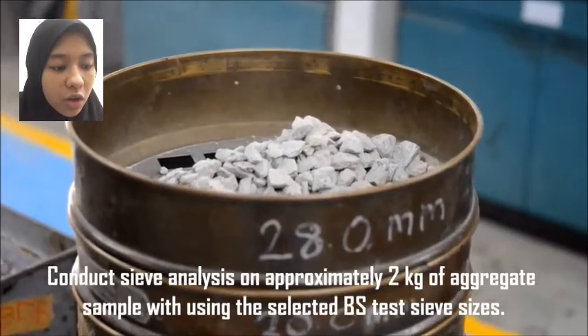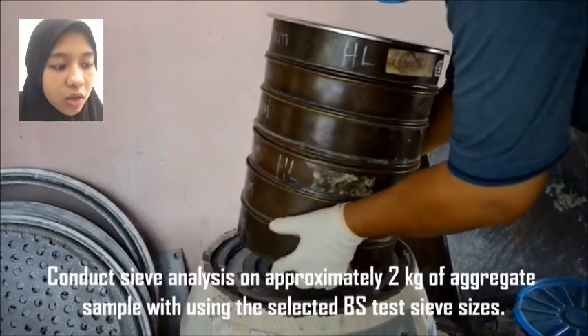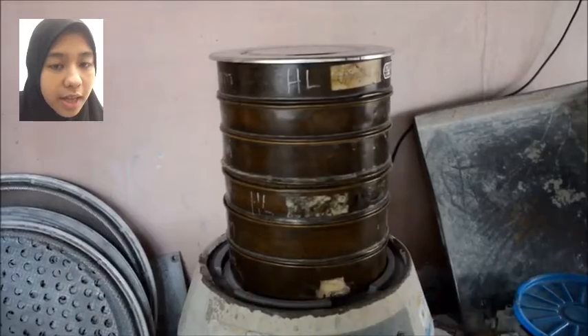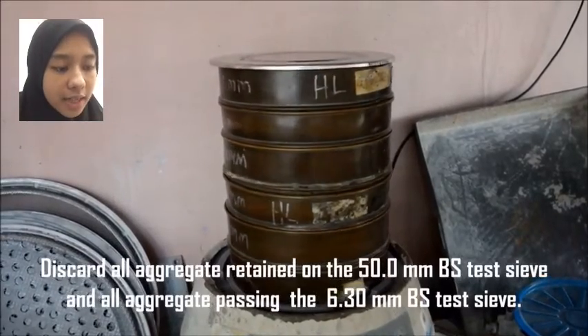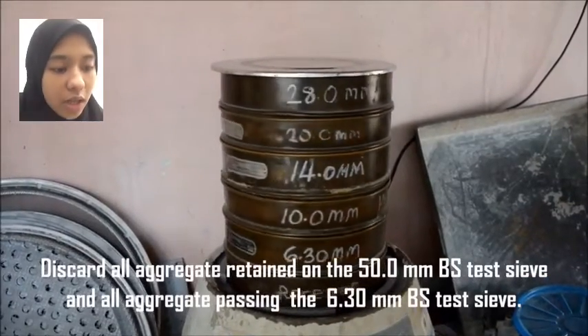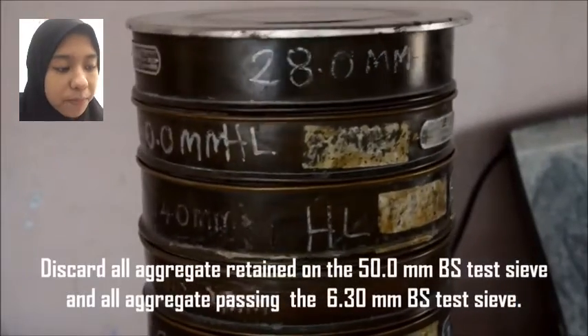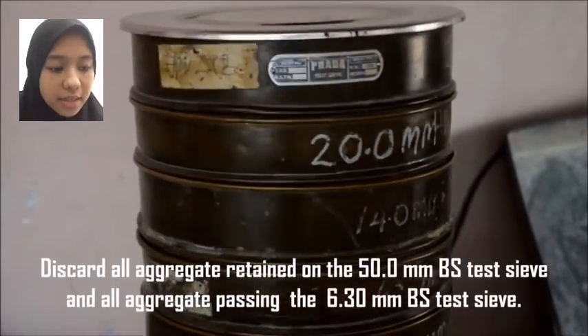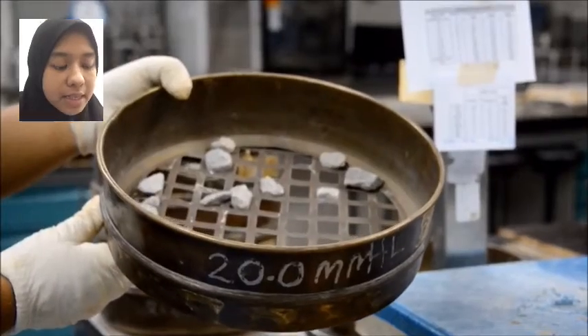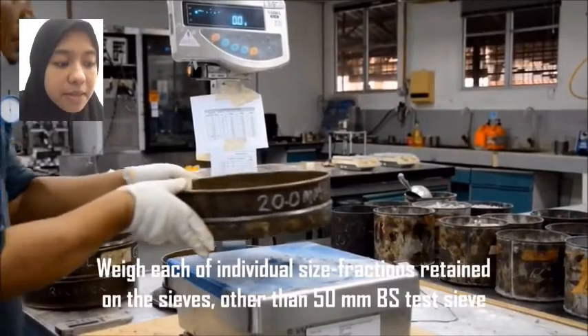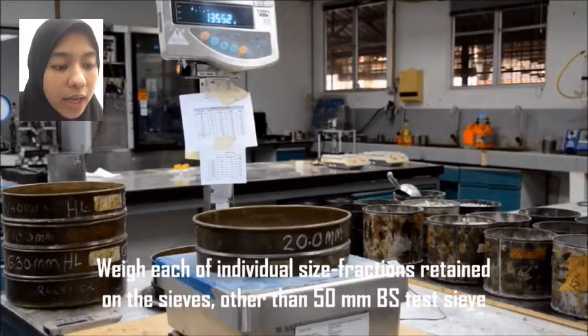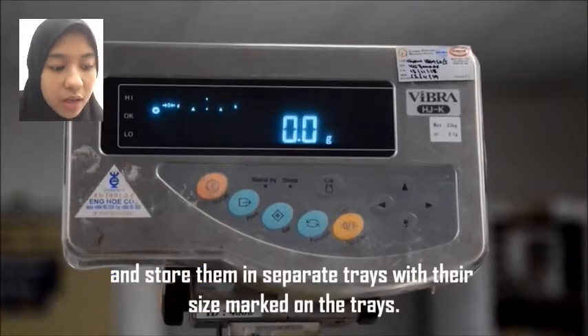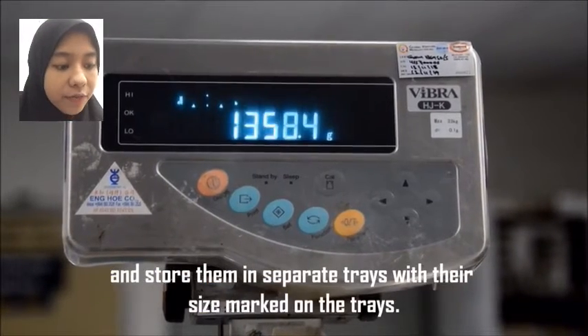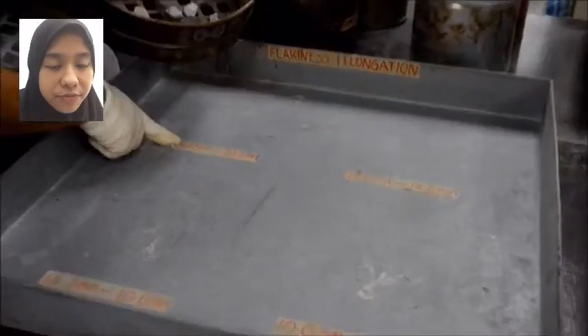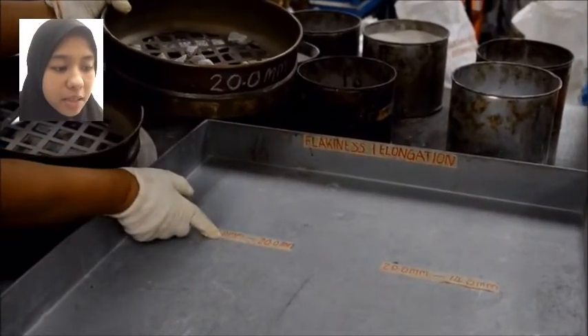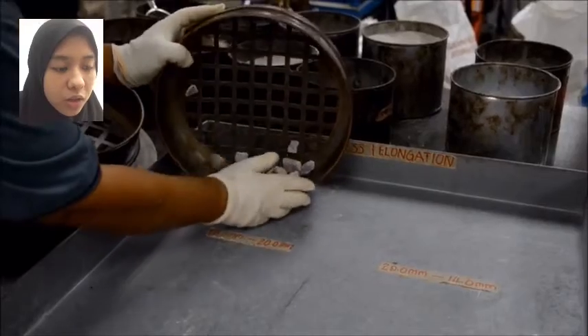Conduct sieve analysis on approximately 2 kg of aggregate sample using the selected BS test sieve sizes. Discard all aggregate retained on the 50 mm BS test sieve and all aggregate passing the 6.30 mm BS test sieve. Weigh each of the individual size fractions retained on the sieves other than the 50 mm BS test sieve, and store them in separate trays with their sizes marked on the trays.